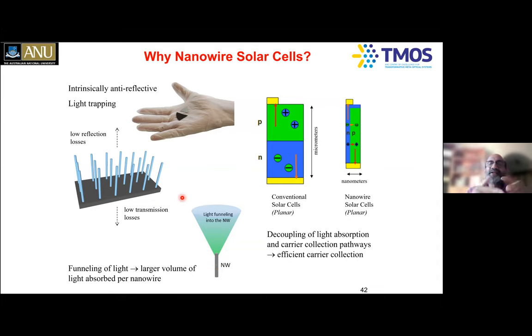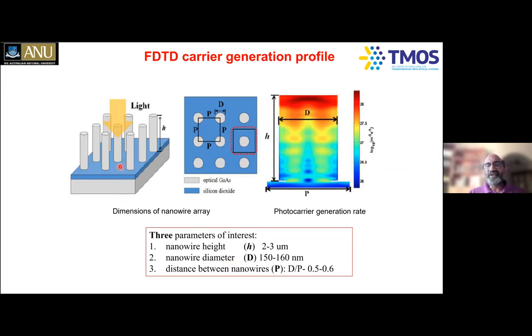That means naturally, you're concentrating the light into the nanowire, which really helps in making use of these things. Again, we spent a lot of time doing simulations of what should be the height of the nanowire, what should be the diameter of the nanowire, and what should be the diameter to pitch ratio, where pitch is the distance between the nanowires. Typically, you only need 2 to 3 micron long nanowires of gallium arsenide or indium phosphide, with a diameter of about 150, 160 nanometers. And then the diameter to pitch ratio should be 0.5 to 0.6 or so. Again, simulations really play an important role.